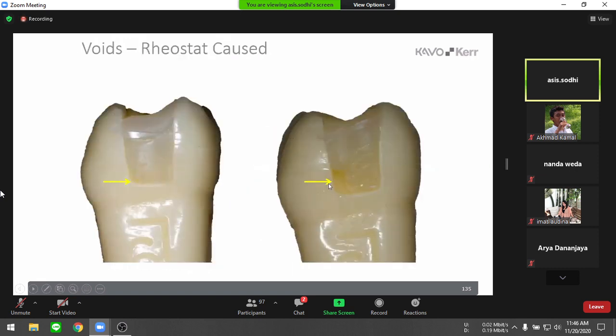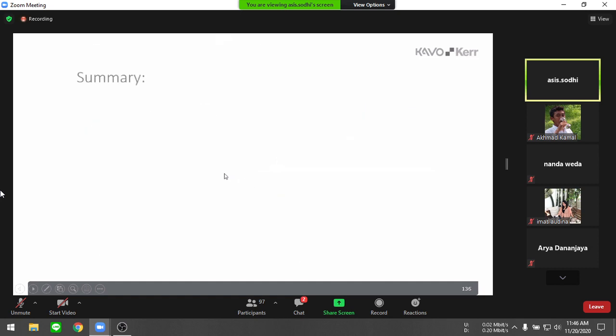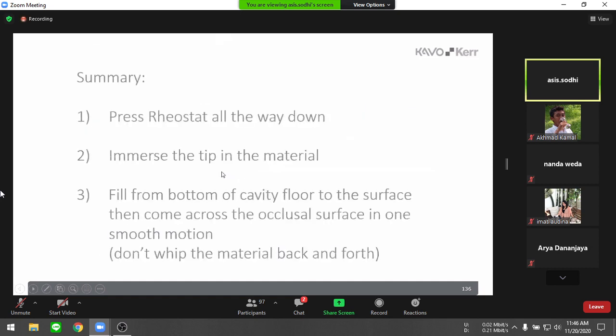Okay, so this is how the voids would look and cause failure of the restoration. So some summary points here also that I've noticed clinicians or users can sometimes miss. It is important to ensure that you press on the foot pedal, your rheostat, all the way through. So you have to activate the handpiece as you start the procedure and keep it activated till the end of the procedure. That is important because that will help you to reduce any void incorporation.